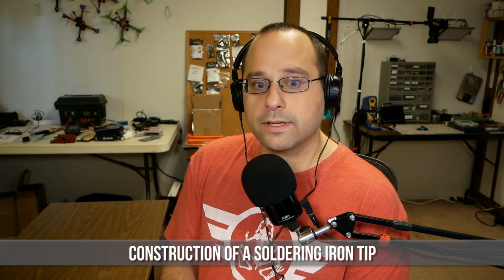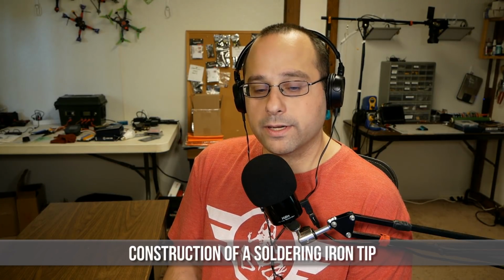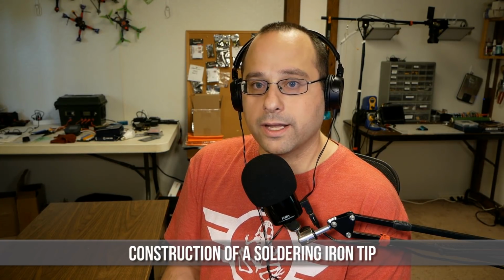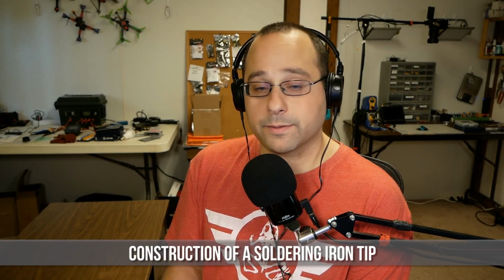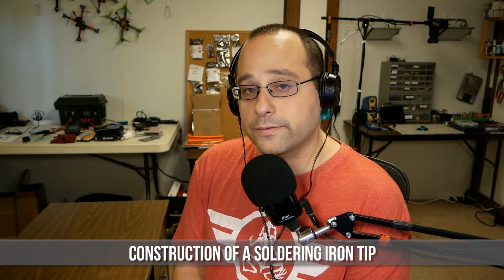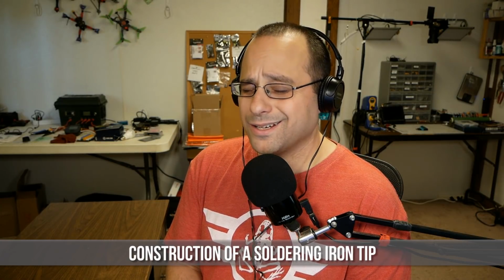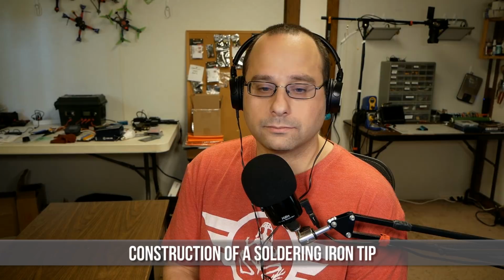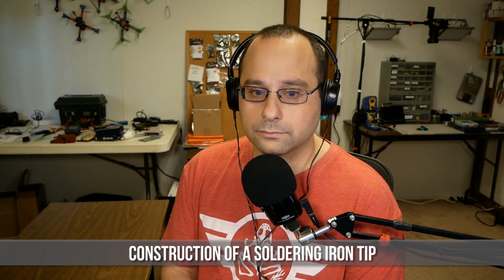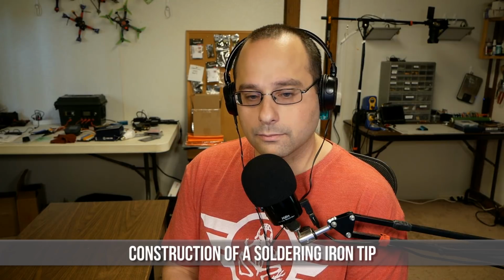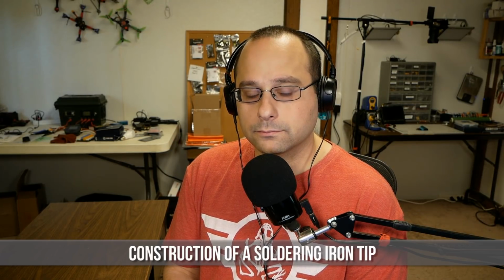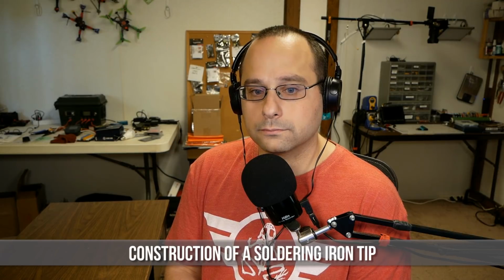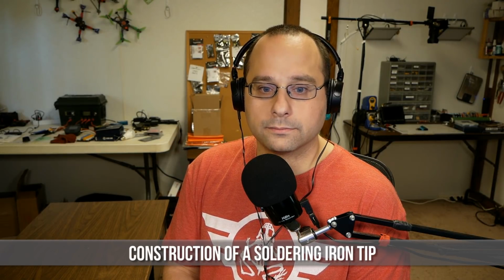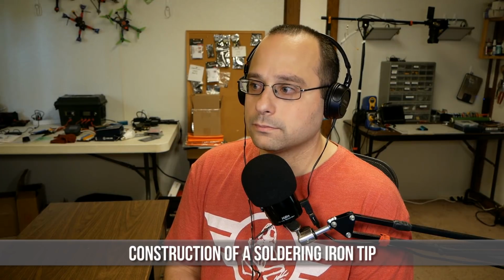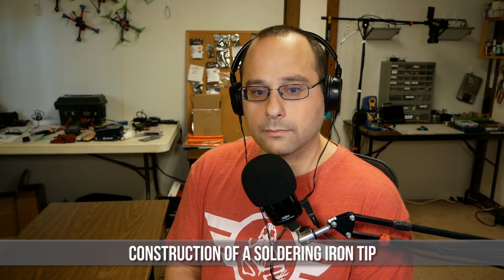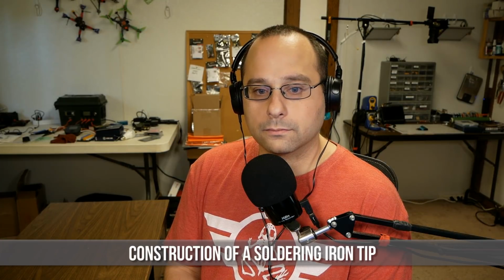It's interesting what you said about the tip being plated, because some people will try to recondition their tip and they'll get out some abrasive, like maybe a piece of sandpaper, and they'll just scrape the oxide layer off. But that's not a good idea, is it? That's probably the worst thing you can do to your tip, is sand it to get rid of the oxide coating, because you're going to wear off the tin plating, and you're going to expose the metal underneath it, which is going to oxidize faster than the tin would have. Right. So definitely do not do that. And that's why we came up with the sal ammoniac block, which has been around in the field for a while as a way of reconditioning your tip.